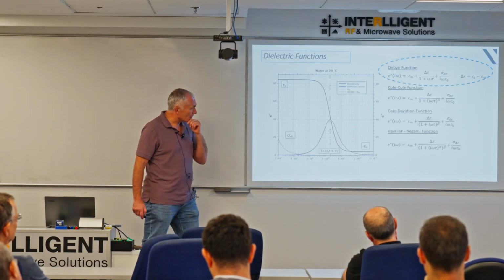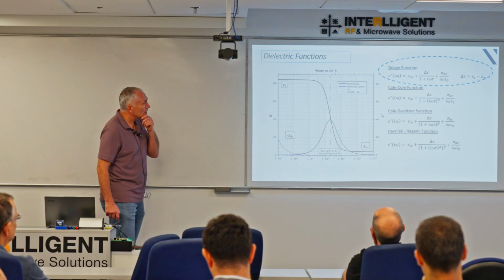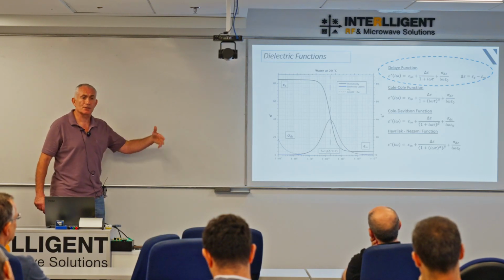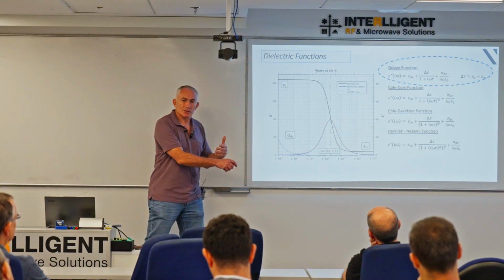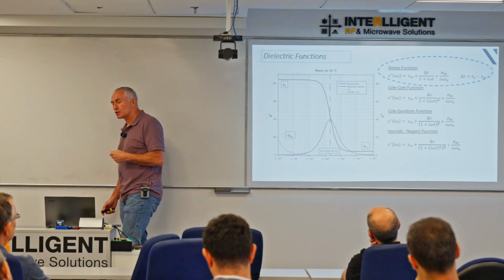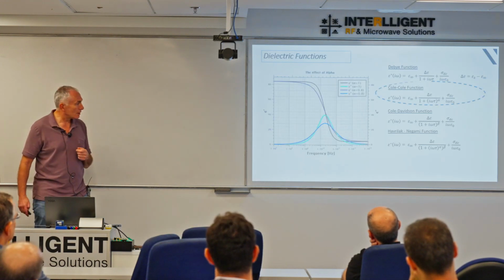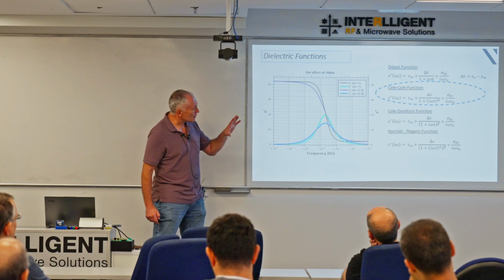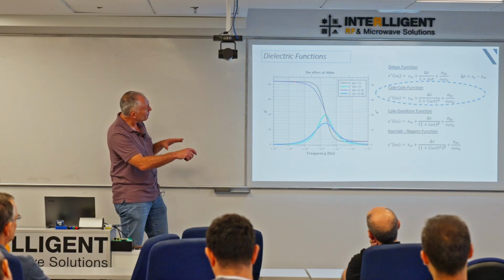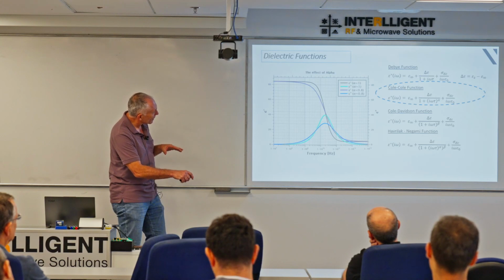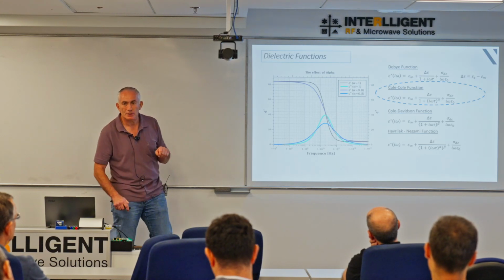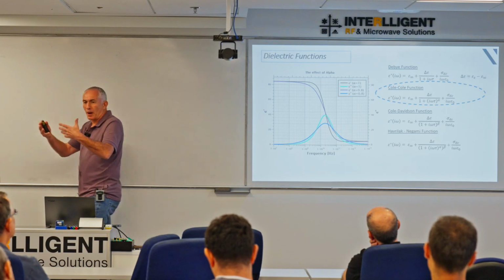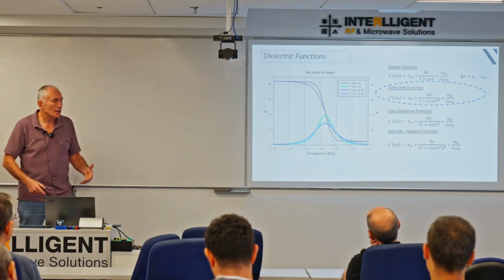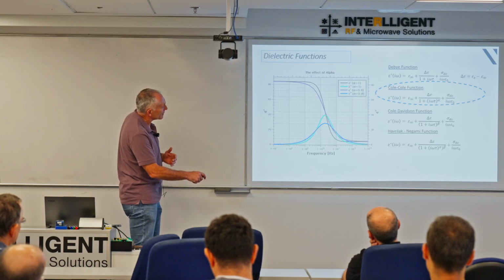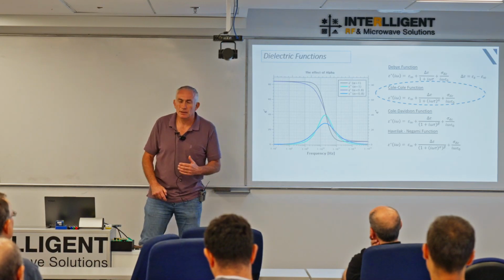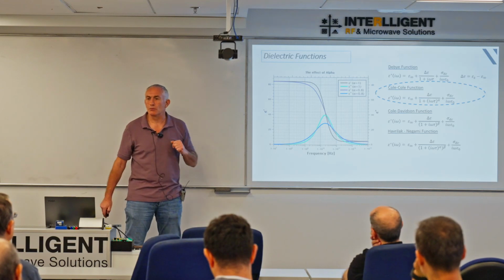Now, in 1941, Kenneth and Robert Cole came out with another function because they noticed an awful lot of materials they were measuring just didn't obey this. They came out with a phenomenological equation called the Cole function, which is this one. The difference is, this black line and this green line, the imaginary component and the real component, show what a good Debye material would be doing, but many of their materials deviated. The peak broadened out and was flattened down.